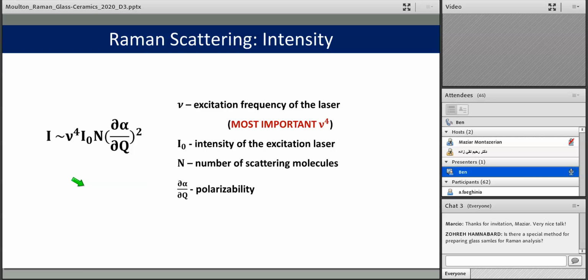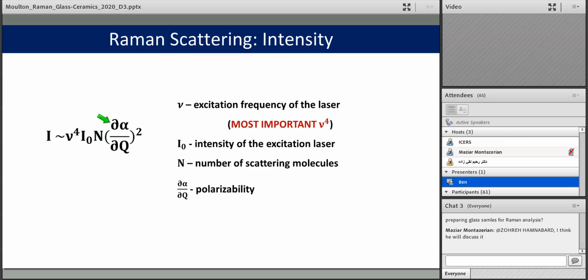Intensity is a bit of a complicated variable in Raman scattering measurements. It is proportional to the fourth power of the frequency, the incident power of the laser itself, the number of molecules or atoms you're exciting, and the square of the polarizability. One of the problems with Raman scattering is that, especially in glasses, we don't know how polarizable the different vibrational modes are. This leads to distortion, where a lot of people focus on the very intense peaks, but they may not have the information we need.